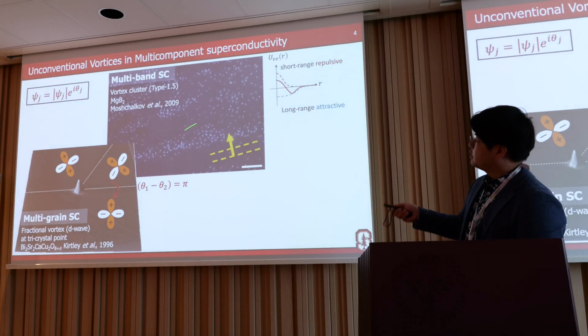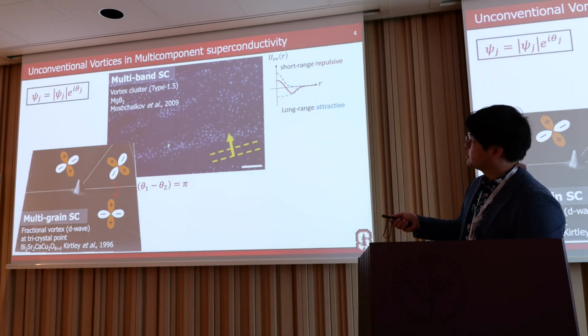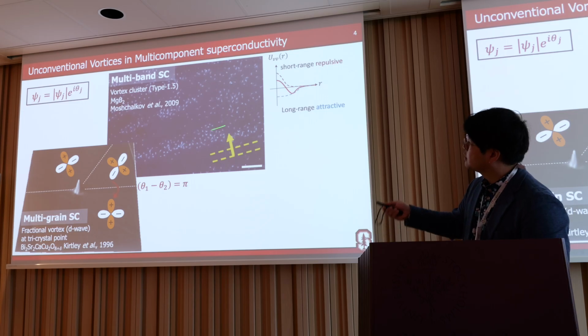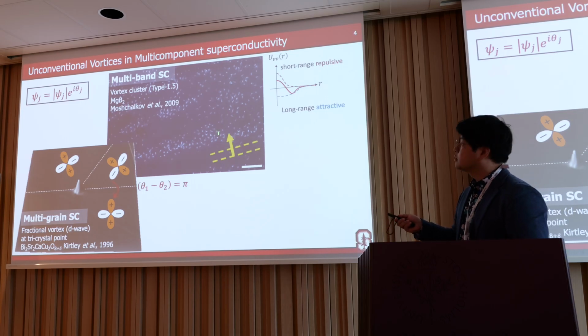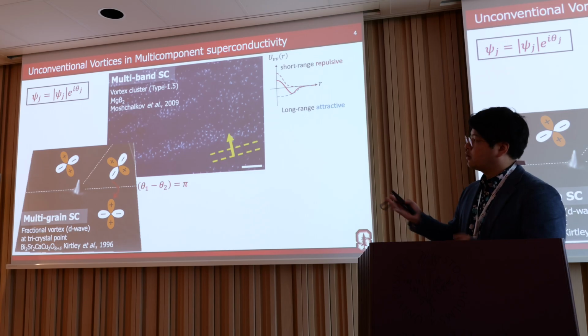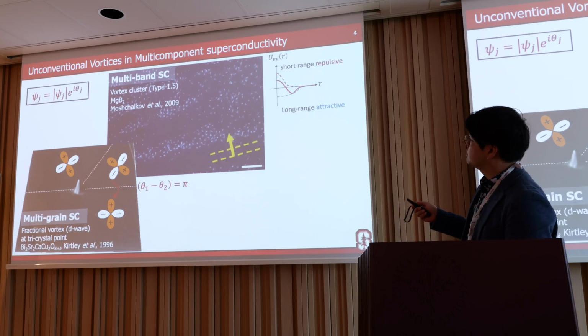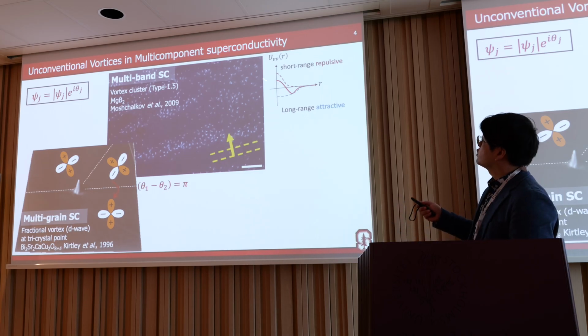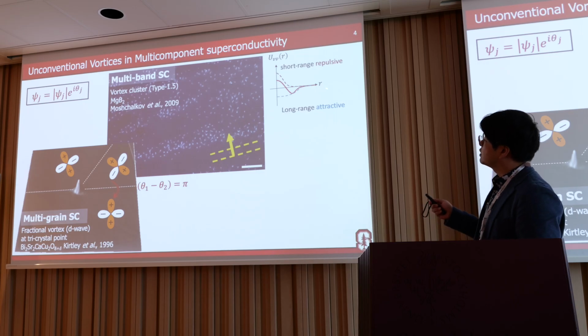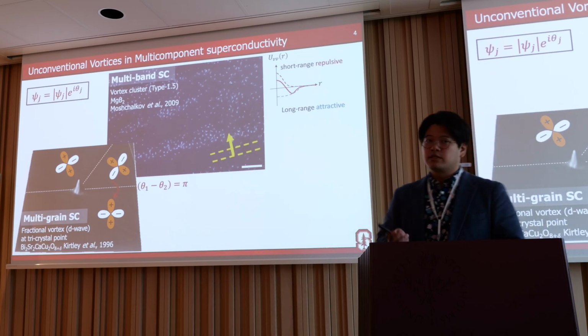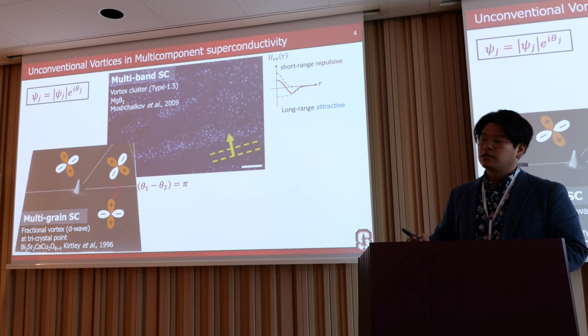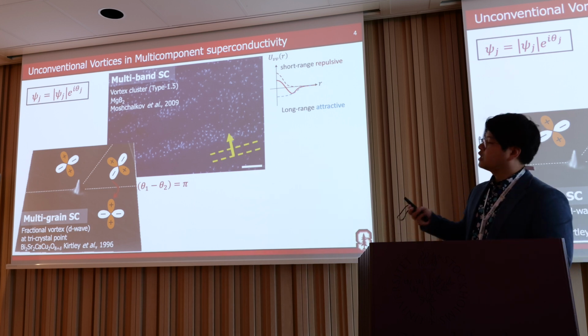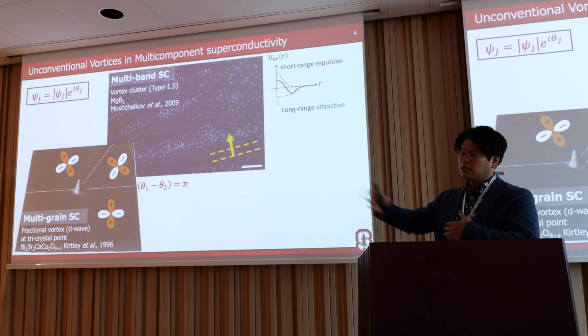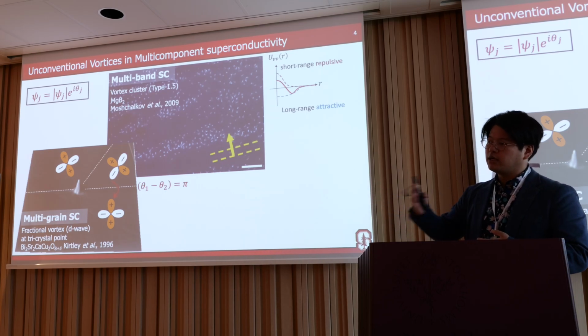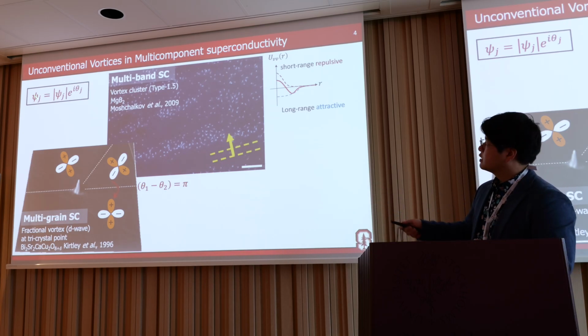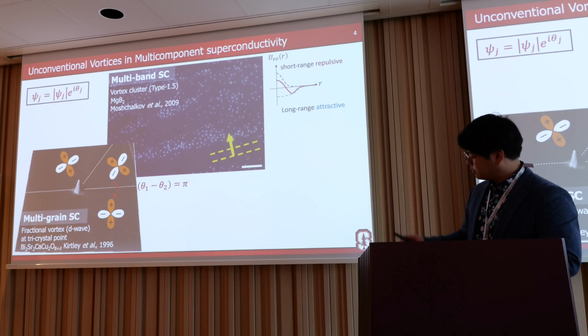Okay, this is a Bitter decoration method to visualize the vortex. It's like clustering in MgB2. It can be understood by a combination of two interactions, vortex-vortex interactions: the short range repulsive and the long range attractive. One explanation is that in the multicomponent theory, one band has a type 1 like coherence length compared to the penetration depth. The other band has type 2. That is the so-called type 1.5 model.